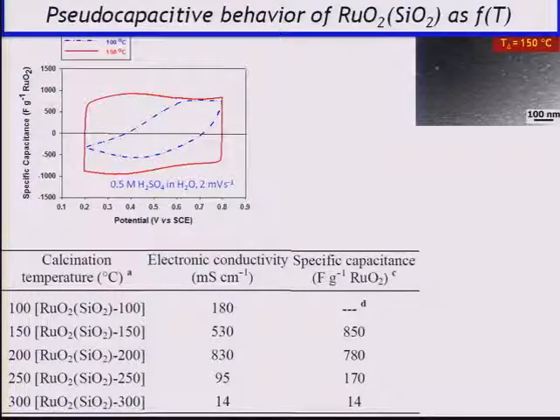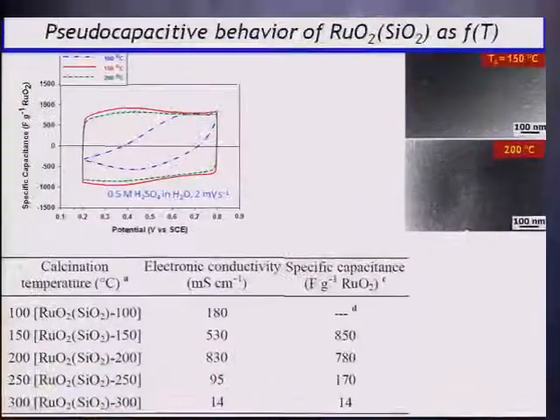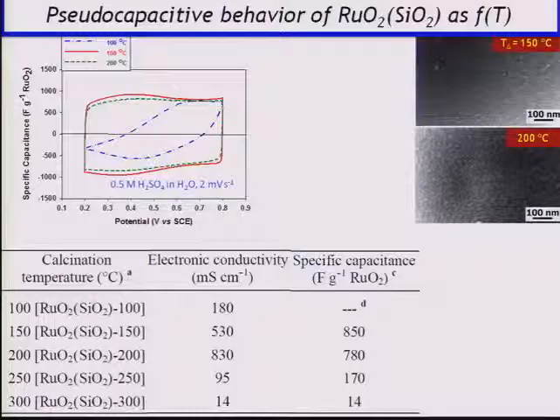So heating at 100 in air improves the conductivity to about 0.2 of a Siemens per centimeter, and you can see it's kind of resistive, so we didn't even try to back out how much charge was stored in there. At 150, you're back to perfection. This is what it looks like in SEM, that packed, fine pebble, monolithic sort of coating. At 200, it doesn't change. There's maybe a little back off in how much charge is stored. There's actually improvement in the conductivity from 150 to 200, from half a Siemens per centimeter to 830 millisiemens per